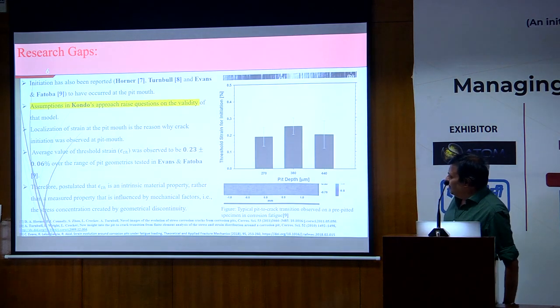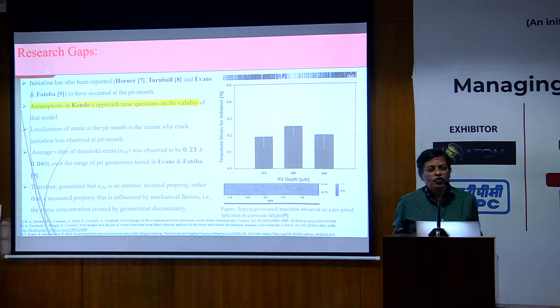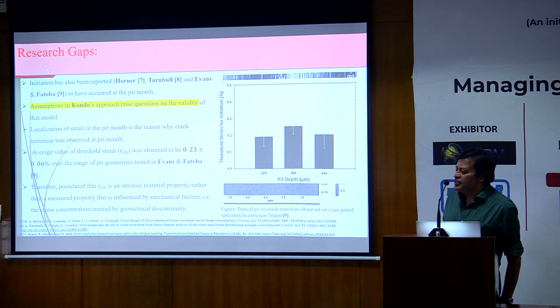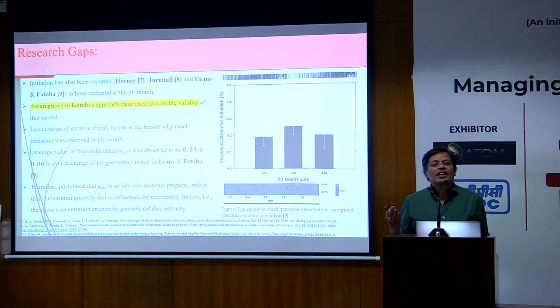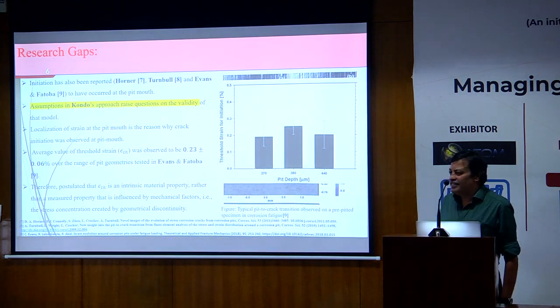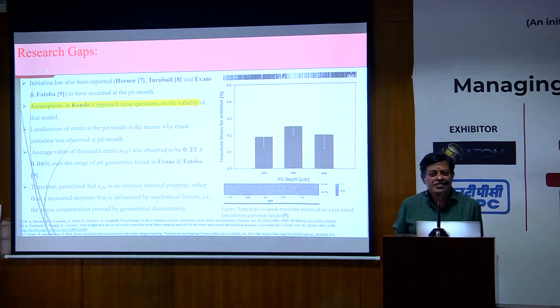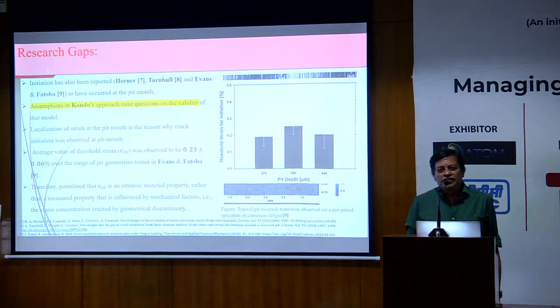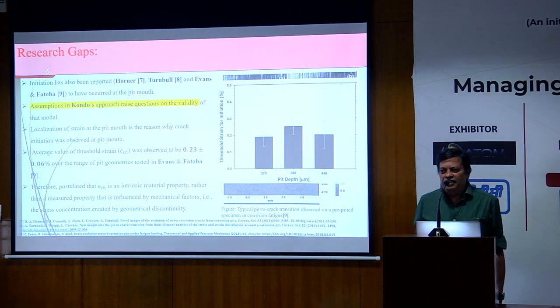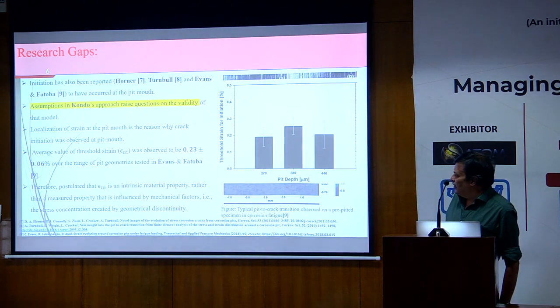Yesterday you saw this slide. So basically, to find the pit to crack transition, what is this criteria? And yesterday, Bob said that they found that at 0.23% strain, as the pit grows at the mouth of the pit, the crack will initiate. And this has been experimentally verified through a number of examples.